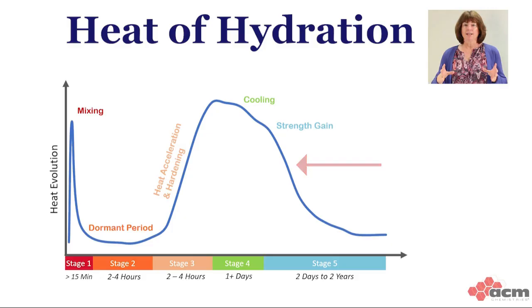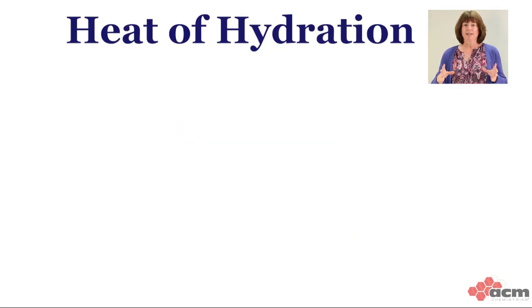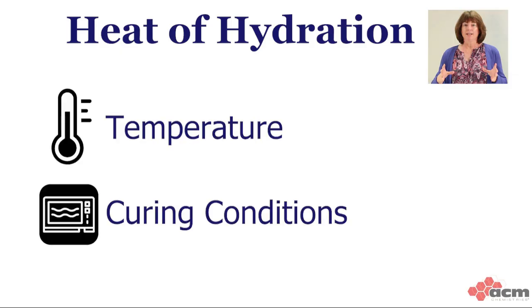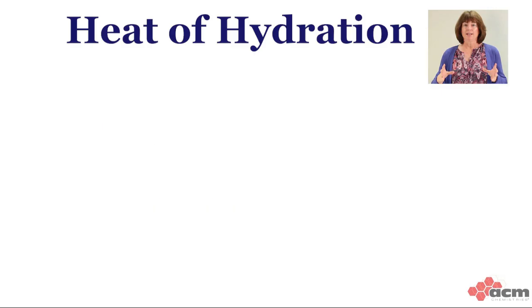While most concrete products achieve the vast majority of their strength in a few weeks to a month, it's important to understand that the cement hydration reaction keeps on going, even after several years, although the additional strength gain does slow down dramatically. It's also important to understand that the cement reactions we just discussed are for concrete made at room temperature. Temperature and curing conditions have a dramatic effect on how fast the cement reactions go and how fast the concrete products gain strength.